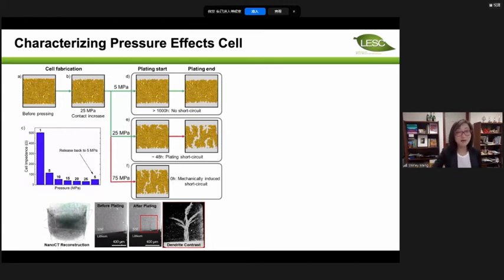So I'll show you a quick example of how bad the situation is. During the synthesis, everything is solid, right? But the problem is they do not have the same mechanical properties. Lithium is soft, sulfide is not so soft, but still a little bit malleable. Oxide is very hard. So during the synthesis, you need to improve contact by increasing the pressure to 25 megapascal. That reduces the contact resistance dramatically. But during the cycling, if you don't release the stack pressure, you run into a problem called mechanically induced shorting of the lithium, because the lithium will creep into the cracks in the solid state electrolyte.